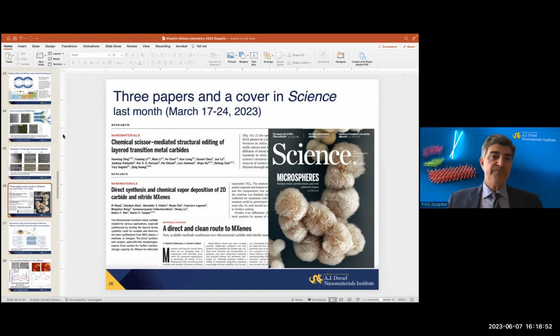So it's good. And if you mill MAX phases, you don't get MXene, but you get something people call MXene. So it's probably 10, 20, 30 nanometer lamellas of MAX phase, which for some applications may be good, for example, for reinforcing metals. So there is nothing wrong with this as long as they give you the properties that you need for your specific application.